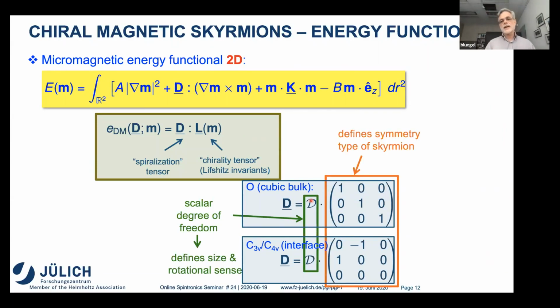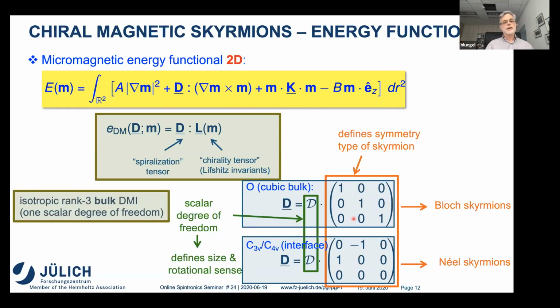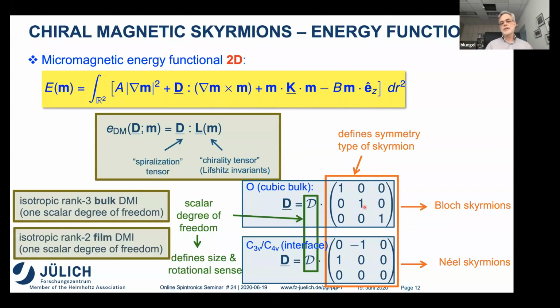And then you have something which defines the symmetry type of the skyrmion due to the symmetry type of the lattice. For example, the upper one here gives you the Bloch type skyrmion. This one gives you the Néel type skyrmion. Both of them are related by a 90-degree rotation. And this one we call isotropic Dzyaloshinskii-Moriya interaction. It's a rank 3 bulk DMI tensor. And in 2 dimensions it is basically a rank 2 DMI tensor because the entry here is 0.